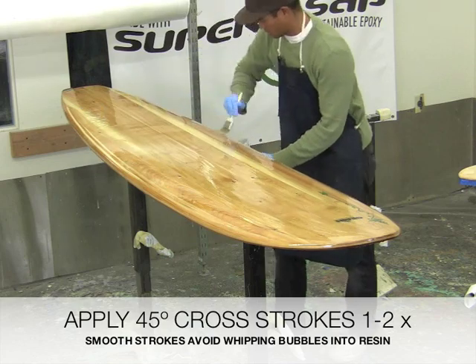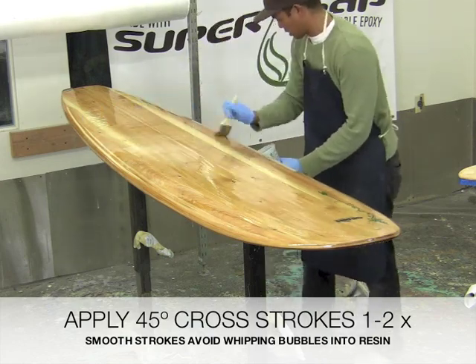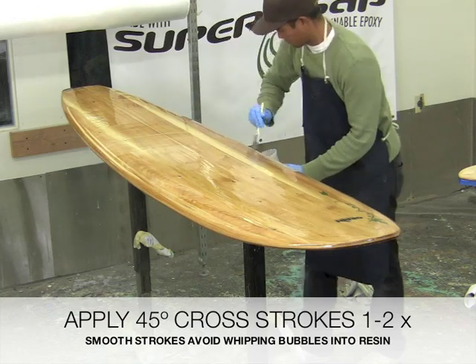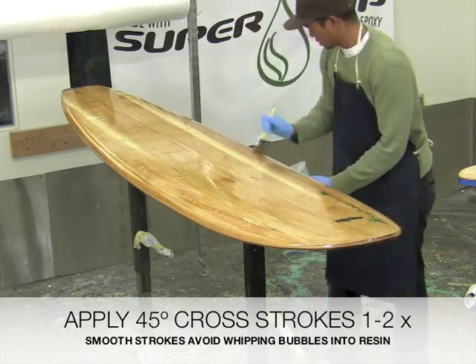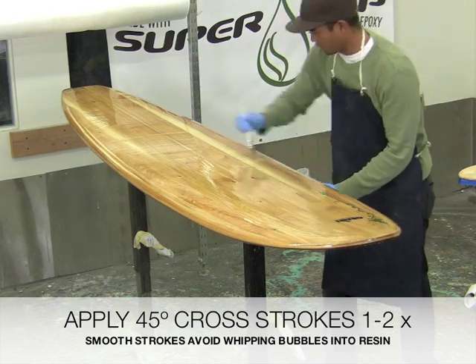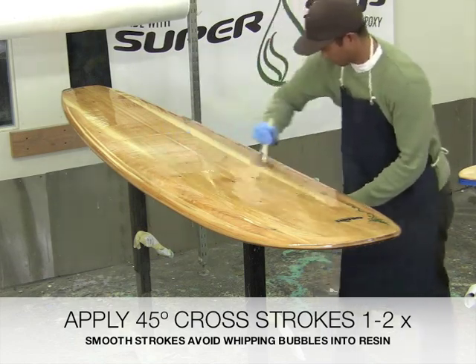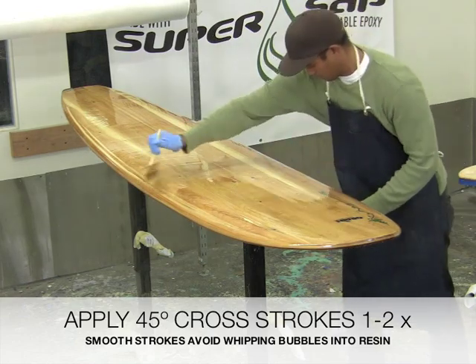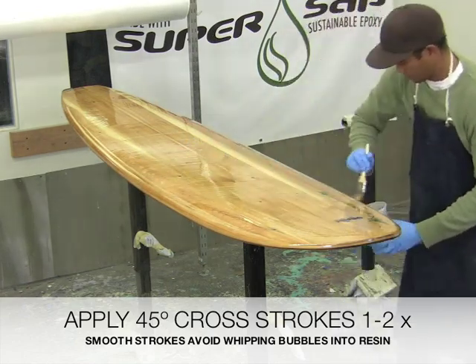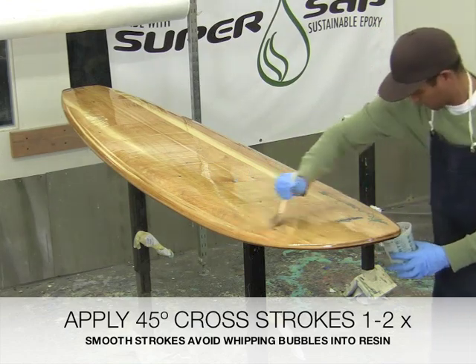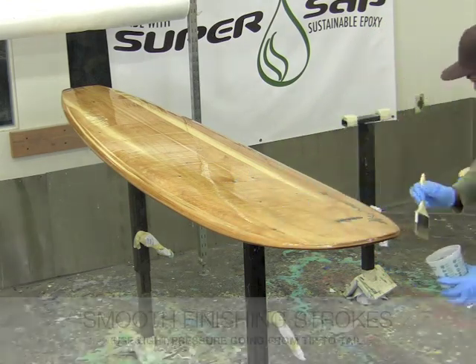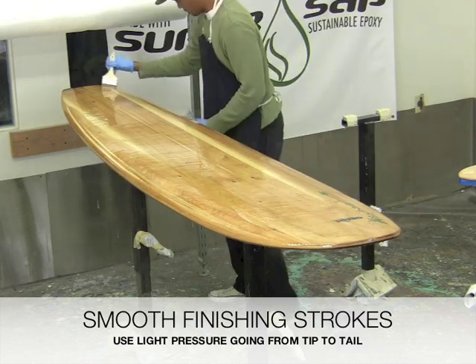Once the entire surface has been coated with resin, come back and apply cross strokes at a 45 degree angle to the center or stringer of the board. Cross strokes are used to help even out your hot coat, but just be sure not to whip the brush too quickly so as not to introduce too many air bubbles.